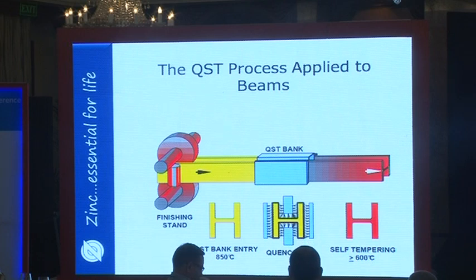The left-hand side is the finishing stand, the last stage of rolling for an H-beam, a typical structural beam. And then it comes out of that at the yellow temperature, which is 850 degrees, and then goes through this QST cooling bank, which you see in the middle, which is a quenching. You can see the quenching sprays on that yellow H in the middle picture there. And it comes out at 600 degrees, after which point it self-tempers as it cools down to room temperature.